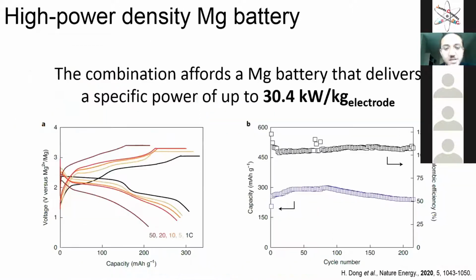So based on this combination of this organic cathode, electrolyte, and magnesium, you can make a magnesium battery that delivers a specific power of 30 kilowatt per kilogram. And this is a record for magnesium batteries. If you talk about organic or inorganic, it is the highest power density published so far in the literature with magnesium batteries. And as you can see, this is the full cell. It's completely reversible. You have 300 milliamp hour per gram, and on the right you have a better stability, more than 200 cycles, which is a good battery.